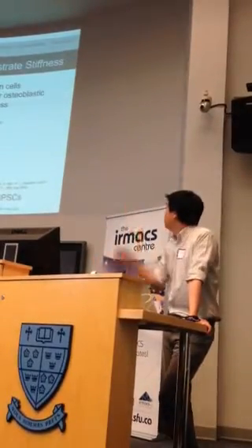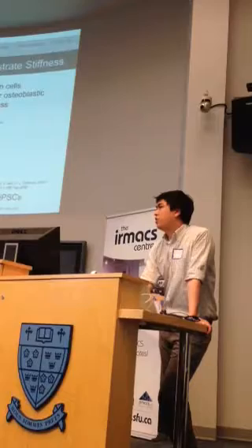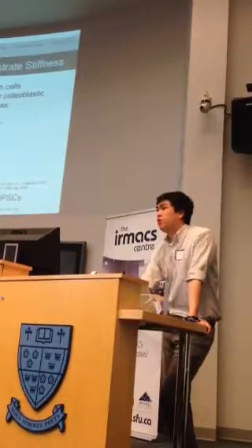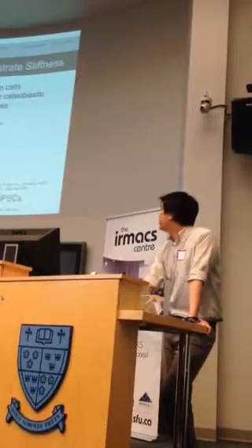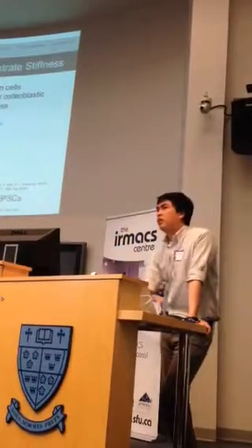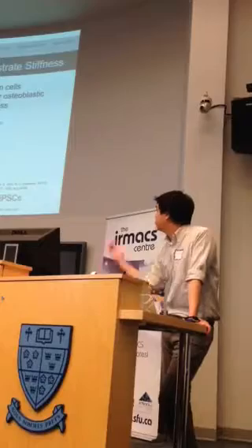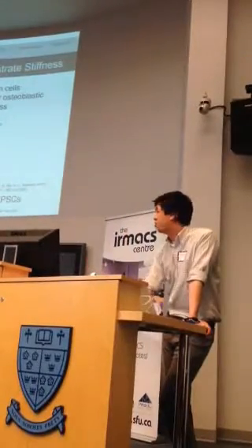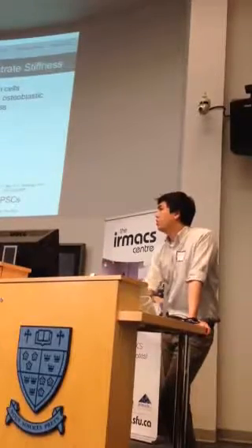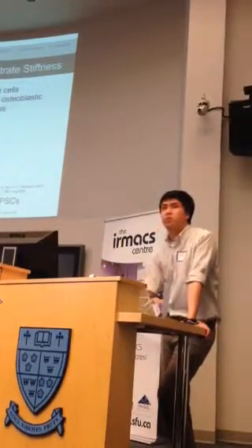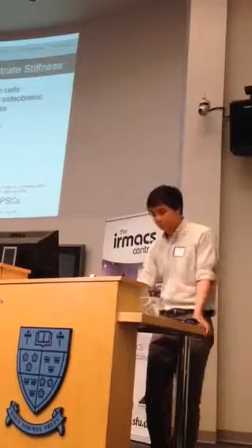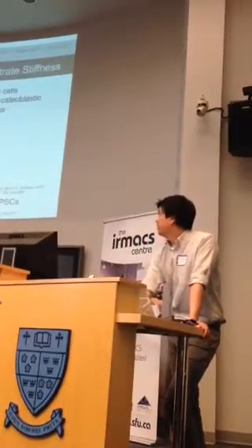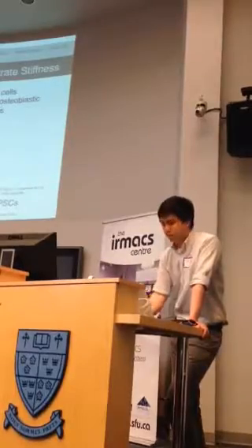So for example, stem cells growing on very soft substrates tend towards a neuronal lineage, which is becoming more like neurons. Those growing on an intermediate stiffness substrate tend towards a myoblastic lineage, a muscle type cell. And those growing on very stiff substrates tend towards an osteoblastic lineage, so bone-like cells. Similar findings have also been reported with iPSCs, induced pluripotent stem cells.